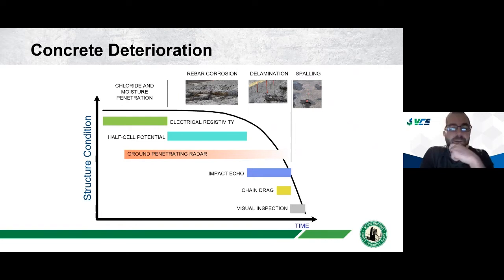And if we recall my early slide, we talked about the two primary methods for investigation: chain drag and visual inspection. But these are really identifying damage in the late stages of that deterioration window. Chain drag and hammer sounding are finding large near surface delaminations. Visual inspection finds surface cracks, spalling, and things like that. While we need to identify these conditions, we will also want to identify damage much earlier, before it gets to this point. If we can repair damage when it's just rebar corrosion before delamination, that'll be much cheaper.